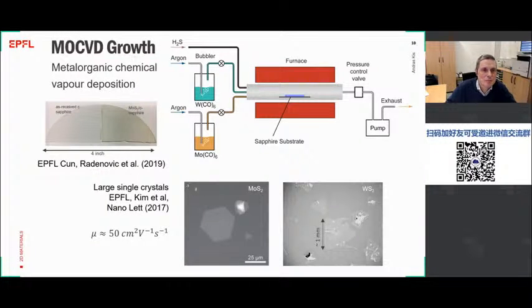And in synthesis, what we have lately been working on is MOCVD growth, so growth using metal organic chemical vapor deposition, where the idea is that we use precursors for growth of 2D materials, which are delivered in the gas phase. For example, if you would like to grow MoS2, molybdenum disulfide, then you deliver into a reactor a stream of argon gas, which carries in it vapors of molybdenum carbonyl. That acts as a source of molybdenum. And then for sulfur, you can use H2S gas. These react close to the surface, and you end up growing large films of 2D material.